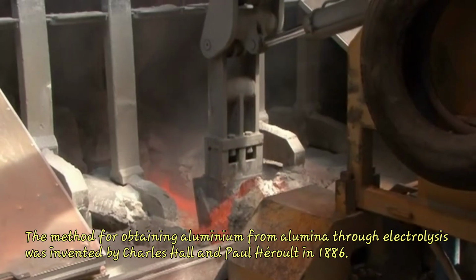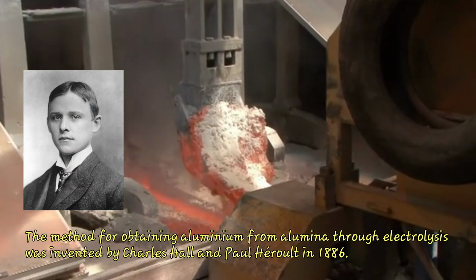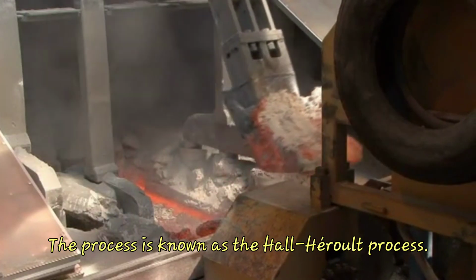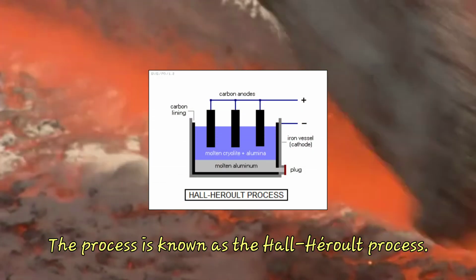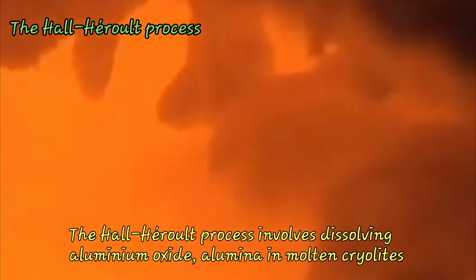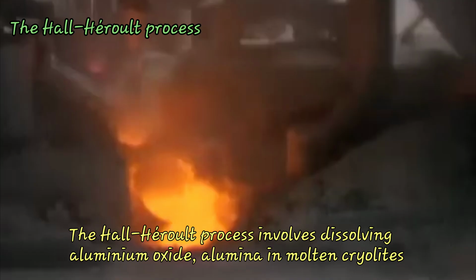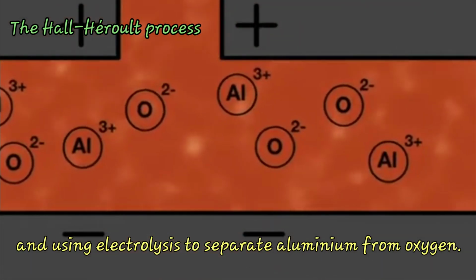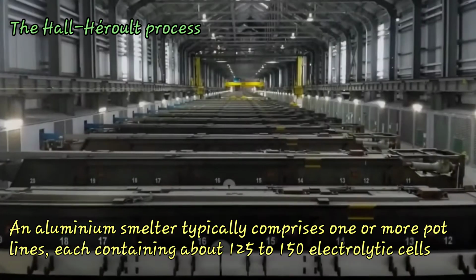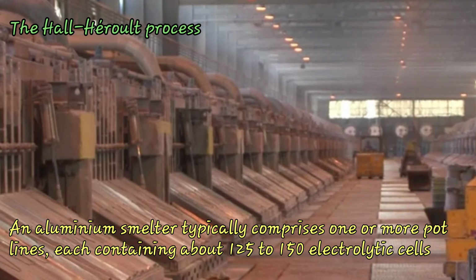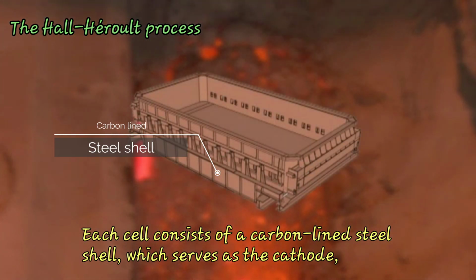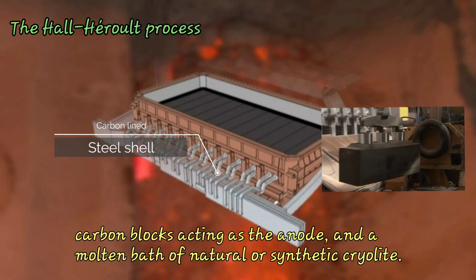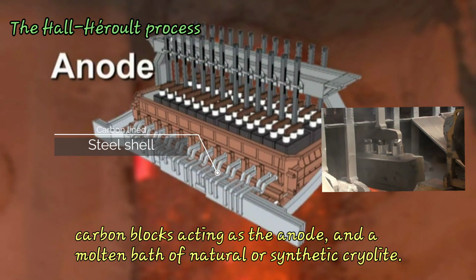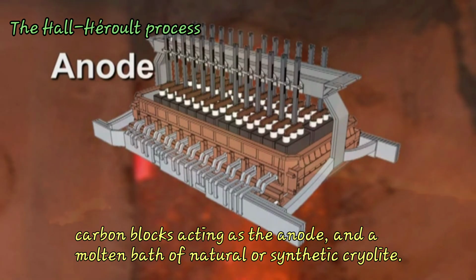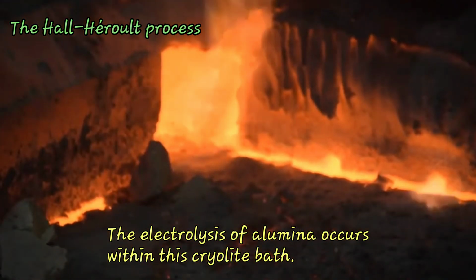The method for obtaining aluminium from alumina through electrolysis was invented by Charles Hall and Paul Héroult in 1886. This process is known as the Hall-Héroult process. The Hall-Héroult process involves dissolving aluminium oxide, alumina, in molten cryolite and using electrolysis to separate aluminium from oxygen. An aluminium smelter typically comprises one or more pot lines, each containing about 125 to 150 electrolytic cells. Each cell consists of a carbon-lined steel shell, which serves as the cathode, a carbon block acting as the anode, and a molten bath of natural or synthetic cryolite. The electrolysis of alumina occurs within this cryolite bath.